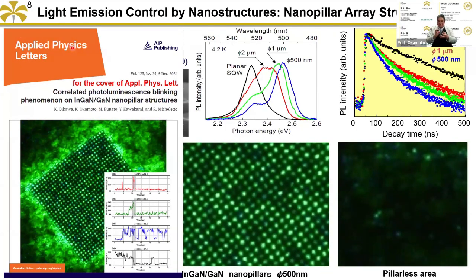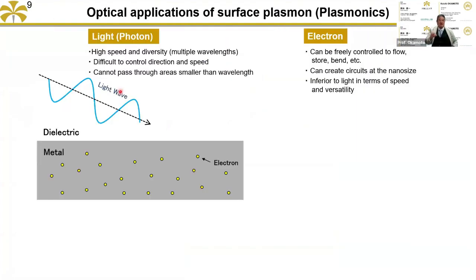Okay. But to fabricate such a structure using E-beam lithography takes a very long time and is very expensive. For example, to fabricate a structure for one wafer, maybe more than one night is necessary. That's why an easier way is important. Then we tried to use the surface plasmon resonance, as Professor Abramovich suggested.